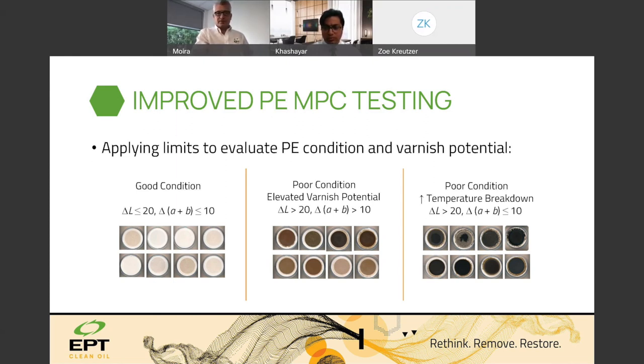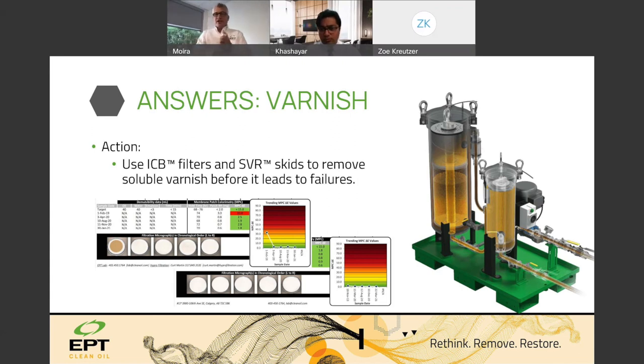Versus chemistry issues. We use the ion exchange resin to remove all that breakdown material in the dissolved form and manage the chemistry and the oxidation of the fluids. In this regard, you can maintain a bright white patch all the time, which will allow you to have the same lubricant properties under all flows, temperatures, and pressures in your mechanical system, which is ideal. If you have a dark patch, the changing temperature, flow, and pressure in your system can force that onto the mechanical surfaces, okay?